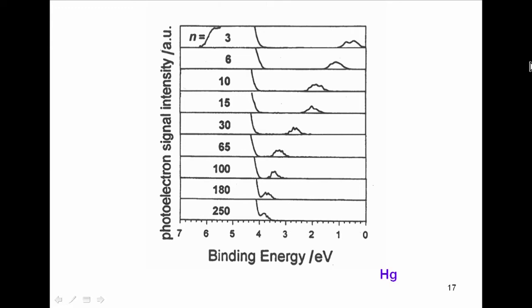In mercury, for example, this is some sort of photoemission spectroscopy. What it is doing is taking different numbers of atoms of mercury and seeing there is a gap between two electron states. That gap is very large when you have 3 atoms, n equal to 3. The gap is smaller when n equal to 6. That means mercury is not metallic. When n equal to 30, still there is a gap between those two features you can see in the spectrum. N equal to 100, still there is a gap. It is only at around 250 atoms that mercury becomes metallic. In other words, any mercury cluster which has fewer than 300 or 250 atoms is non-metallic.